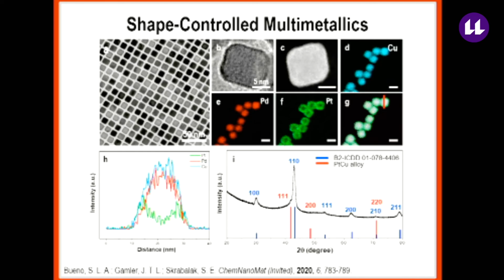And so the seed-mediated co-reduction approach does work. Here is the example where we took those palladium-copper intermetallic nanoparticles and built platinum-copper alloyed shells on top of them. And we get very good shape control. The core shell architecture is evident here in the line scan. There are two different phases in the powder diffraction corresponding to our core and our shell.